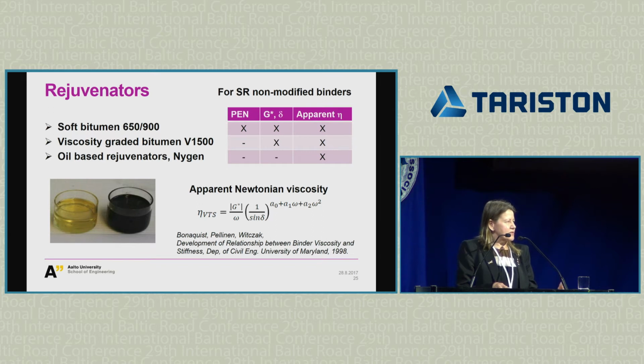So there's this apparent Newtonian viscosity, an empirical equation that was developed almost 20 years ago at the University of Maryland when these superpave performance models were evaluated. It gives you a viscosity estimation based on G star and sine delta, and then you need to have a correction for this phase lag. It's highly frequency dependent because you are not in the Newtonian area anymore.